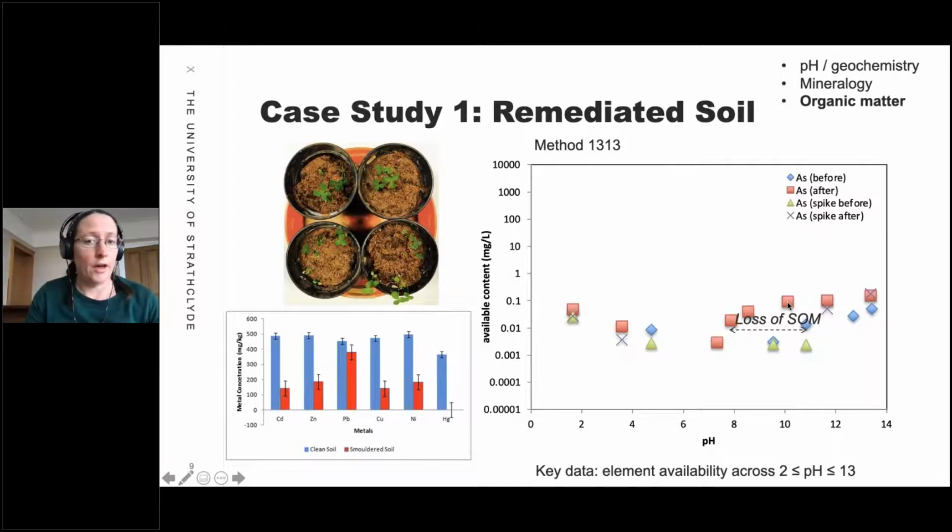This is arsenic, we didn't add any. It's a very trace level of contamination that's present in the soil. I think it's below what would be considered as just naturally occurring there, but we are making it slightly more available because by smoldering, by combusting the organic contaminant that was there, we destroyed the natural organic matter where that arsenic was partitioning. So that's one visual difference that's apparent.